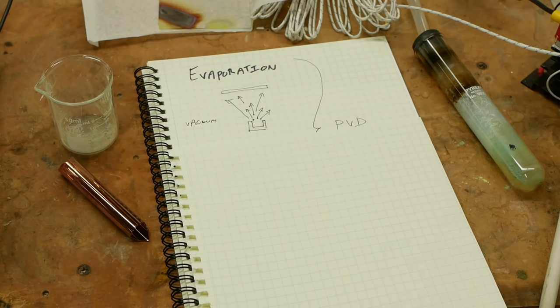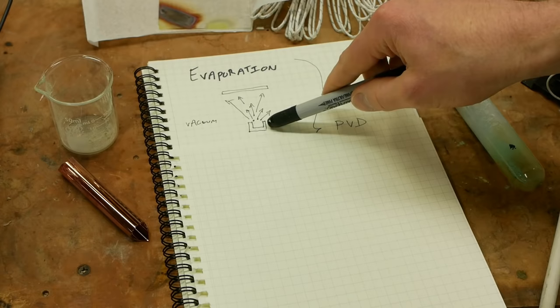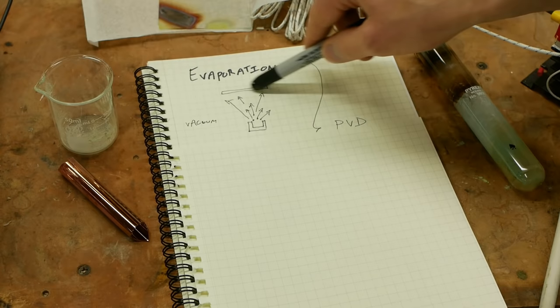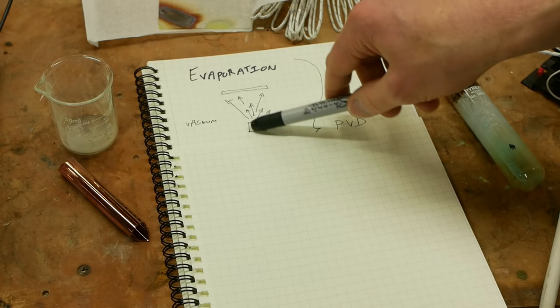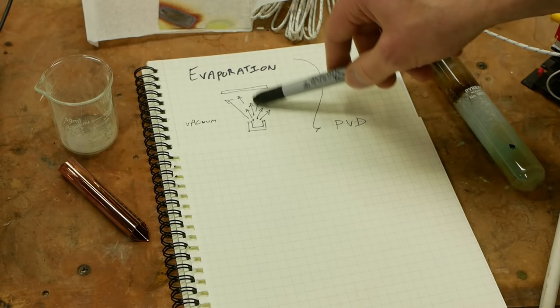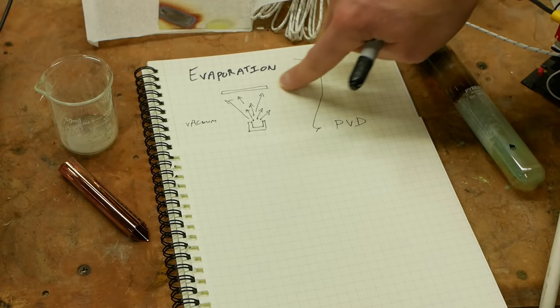Let's take a quick look at some of the other techniques to make a coating on something. And then you'll see why ALD was such an exciting technique, if it works. So in the beginning, there was evaporation. And the way this works is you just take a material and heat it up in a vacuum. And eventually, as far as I know, all materials vaporize when you get them hot enough. And the atoms or molecules fly out of your hot pot of stuff here and go in a straight line and hit the substrate, the thing that you want to coat, and freeze there.